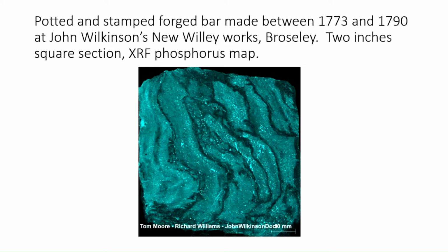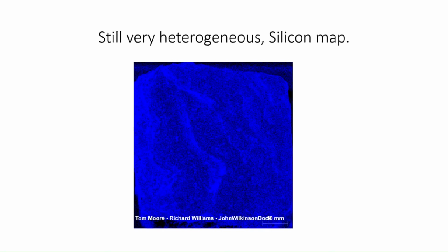This is a solid piece of iron. You're not looking at iron with any sort of gaps between it. What you are looking at is areas where there is no phosphorus. Because when this was put in the crucibles in the solid state, the phosphorus was removed from the outside of the iron, and that showed up when you put it under a phosphorus map when it was beaten into this shape. I found that was really fascinating. The stuff was still very heterogeneous because this is a silicon map, and you can see there's a variation in silicon content, actually very much mirroring the difference you got.